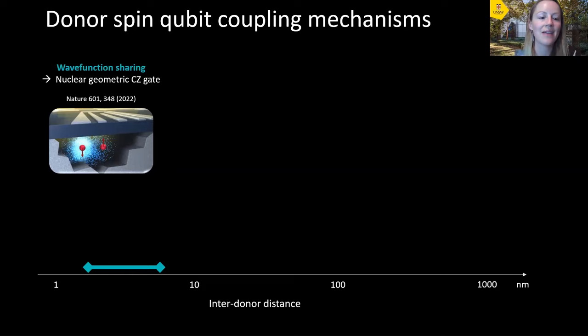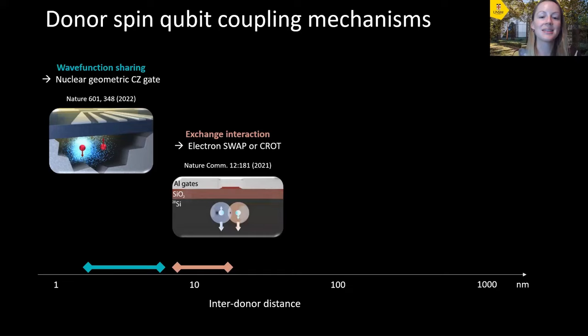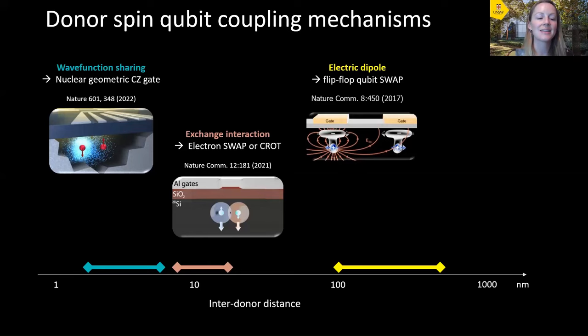And then if the donors are spaced slightly further apart, so on the order of 10 to 20 nanometers or so, each donor will have their own electron that can be coupled to each other through the electron exchange interaction. And then looking to longer length scales, we can also create a so-called flip-flop qubit from the combined state of a nuclear spin and an electron spin, and use the electric dipole interaction between these flip-flop qubits that allow us to space out our donors to 100 nanometers and more apart.